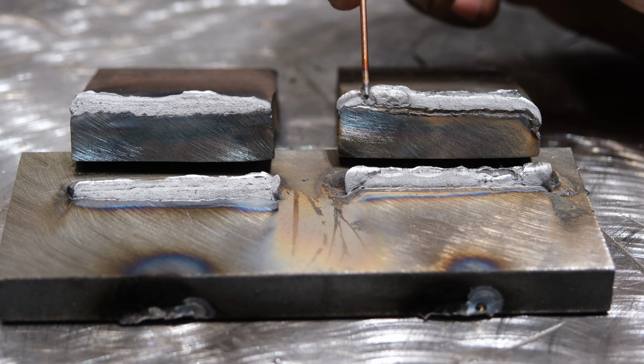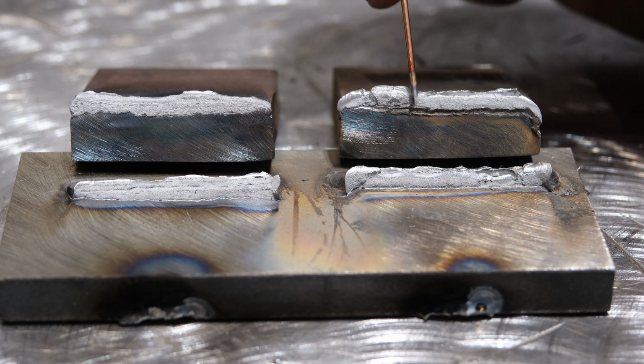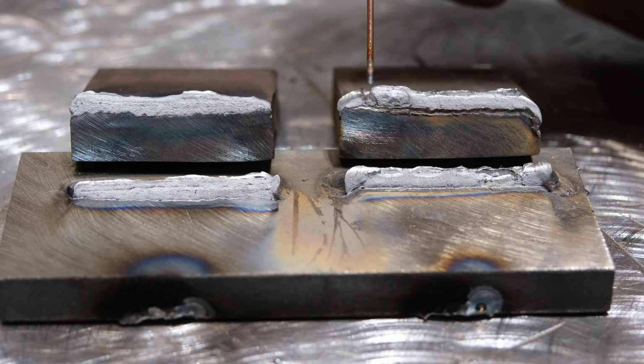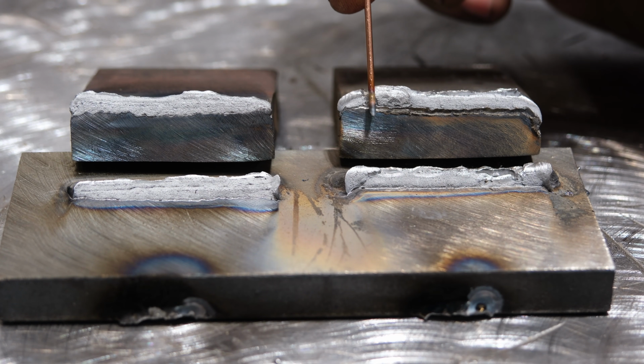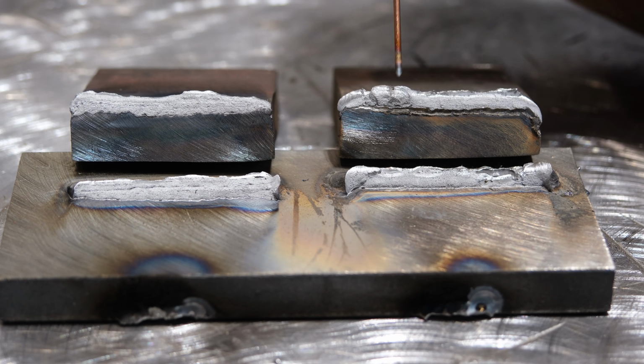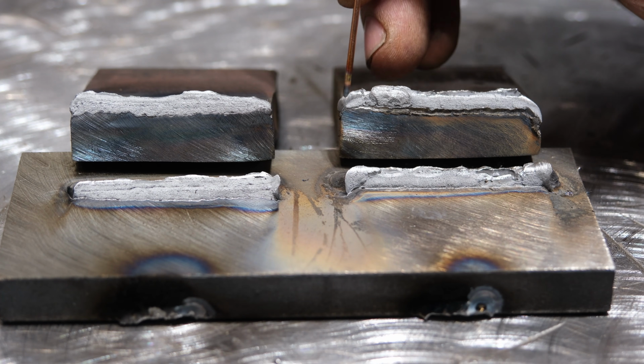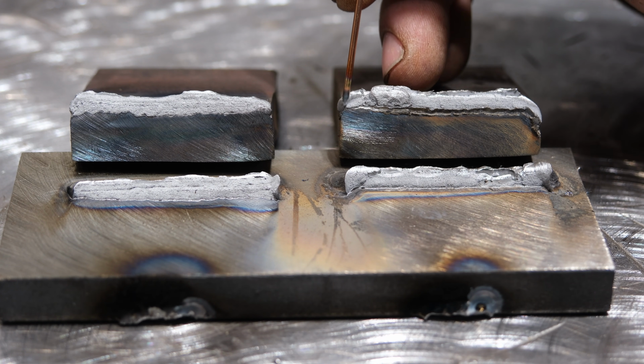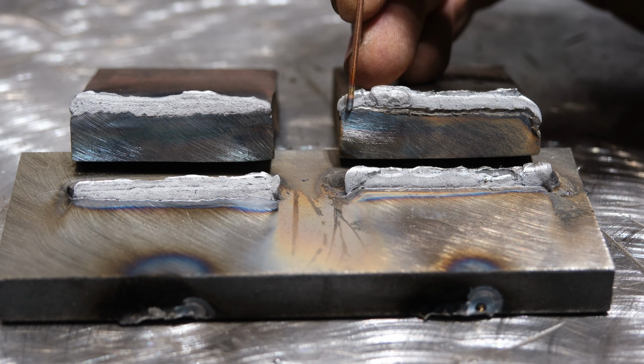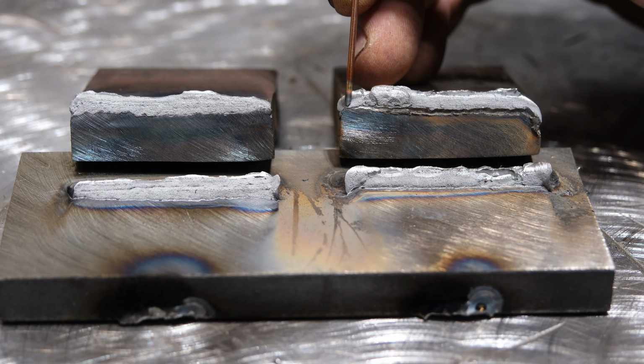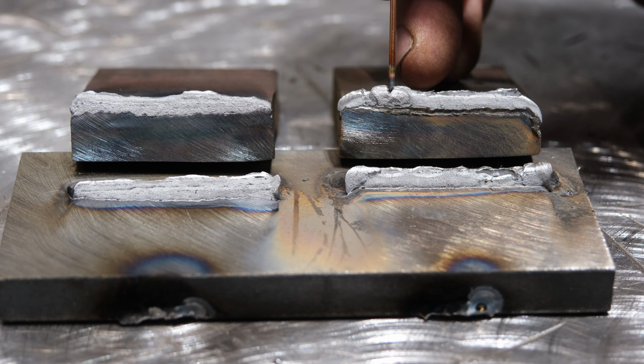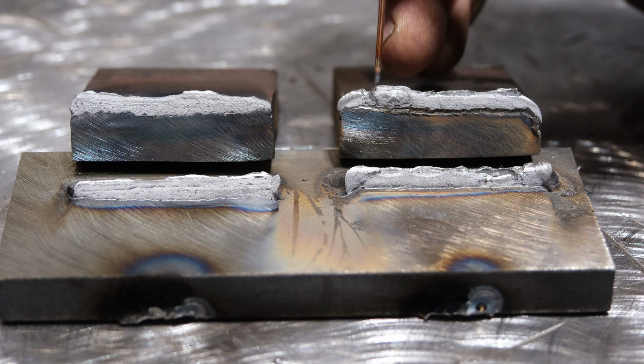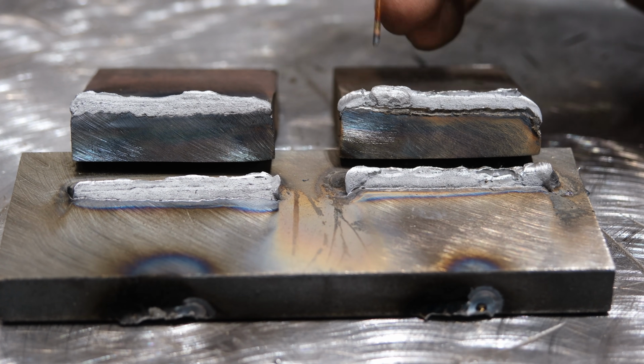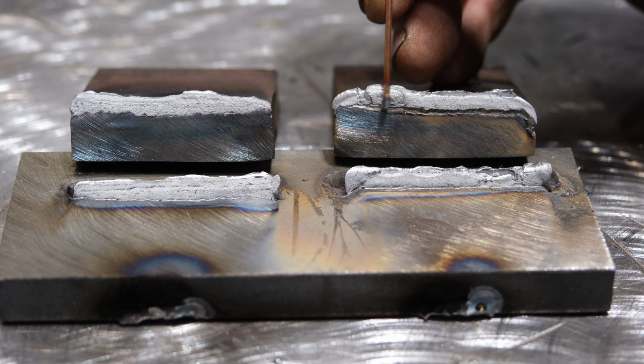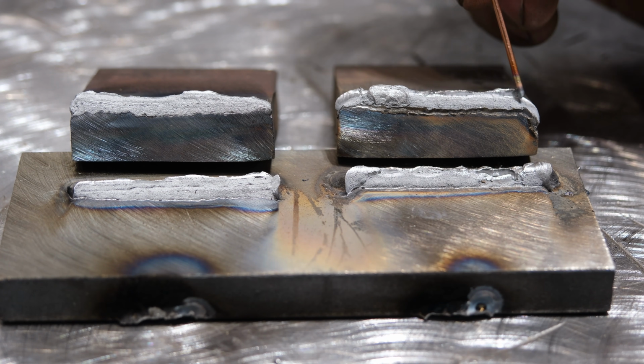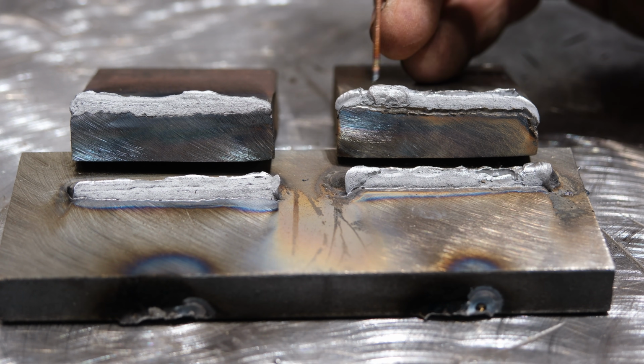Anytime you stick weld, that first about 3/16 to about 3/8, so somewhere, I don't know, maybe 2.5, 3 mil to about 5 millimeter, that area is going to have a lack of fusion. And that is because you start on a corner, there's nowhere for the heat to escape. That typically will fuse decently, especially with hot start like the machine has that I welded. And then when you get moving, that molten pool cools down a little bit, and you're trying to weld through a less hot molten pool, and then you end up with this lack of fusion here.